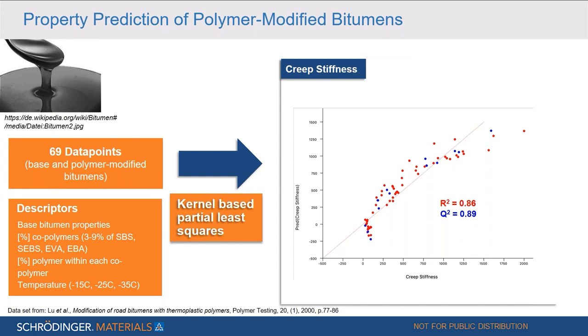In this case, for the machine learning, a total of 69 base and polymer modified bitumens with experimental measurements were taken. And different descriptors like base bitumen properties, the percentage of copolymers, the composition of the polymer, and 3 different temperatures were used.